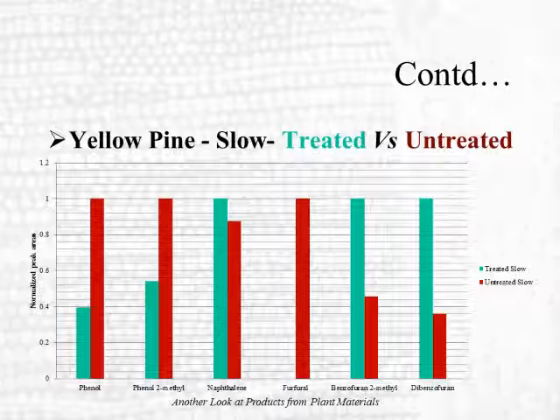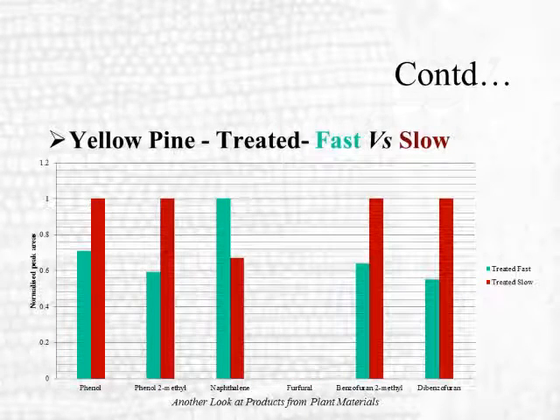Okay? And if we look at slow, instead of fast heating, slow heating, we saw a little bit of difference, but by and large, treated versus untreated, you've got this compound going away with sulfuric acid treatment, and then these compounds coming out in a greater amount with treated. Again, the furan compounds. So it happens whether you go fast or whether you go slow. Okay, and then just treated wood, fast versus slow, just the sulfuric acid treatment. And we see a little bit of difference in the amount of compounds that come out, whether they're heated slow or heated fast.